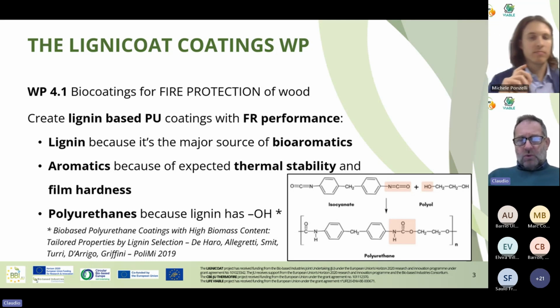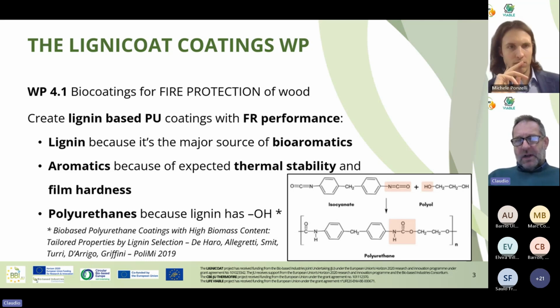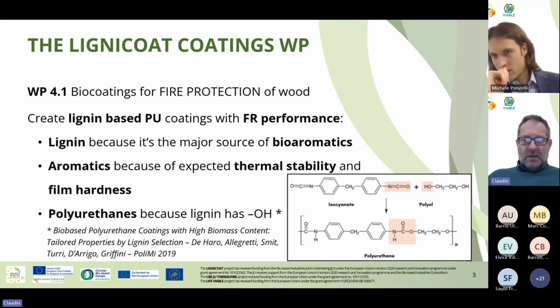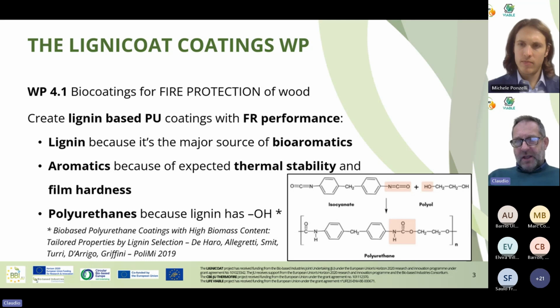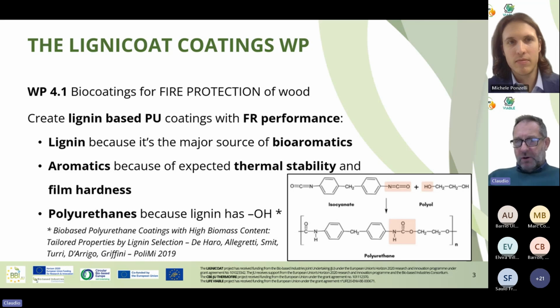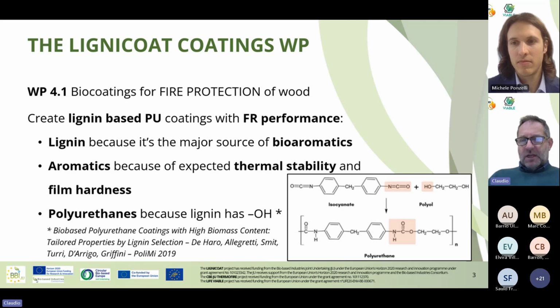But the other point to us fire people, you can discover that lignin in particular has a good thermal stability. For example, by running thermal analysis, TGA, and comparing different types of lignins with conventional polyols, you discover that the thermal stability of lignin is higher than, of course, aliphatic polyols. And this gives us a hope that the final product will be inherently more resistant to the flames.